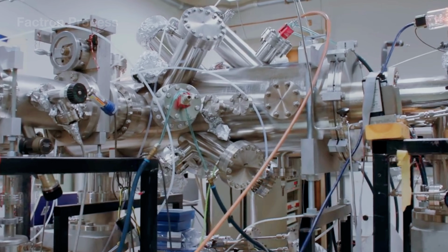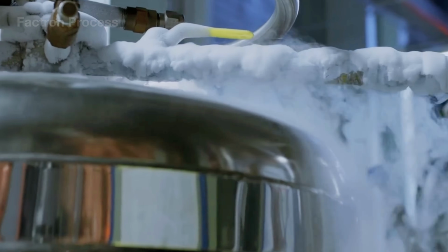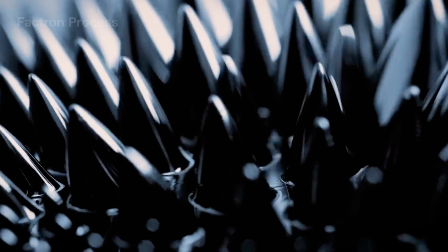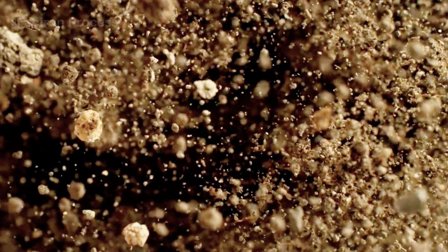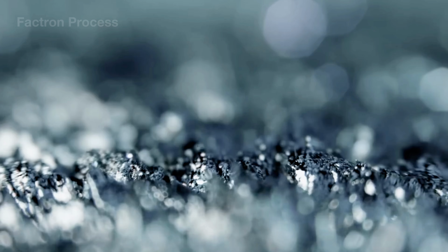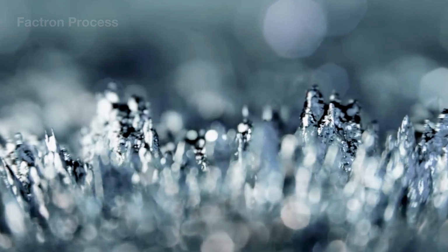Because rare earth ions have similar sizes and chemical properties, the solution is pumped through a countercurrent solvent extraction system consisting of hundreds of mixer-settler stages. At each stage, the organic and aqueous phases are mixed and then separated, gradually isolating neodymium and praseodymium from the remaining elements. The NdPr stream is then precipitated as oxalate and calcined into an oxide powder with a purity above 99.5%.